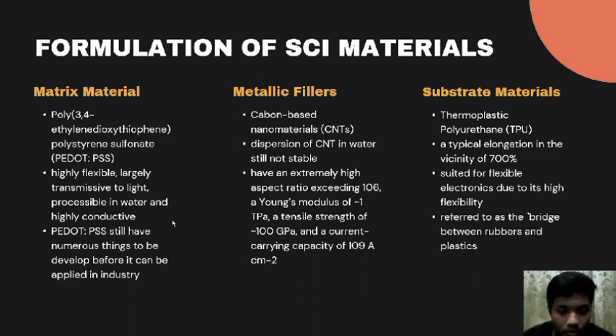There is also the occurrence of toxicological problems. CNT also has an extremely high aspect ratio exceeding 10 to the power of 6, a Young's modulus of 1 terapascal, a tensile strength of 100 gigapascal, and a current carrying capacity of 10^9 ampere per centimeter squared. These superior properties make CNTs a fascinating nanomaterial for stretchable conductors.